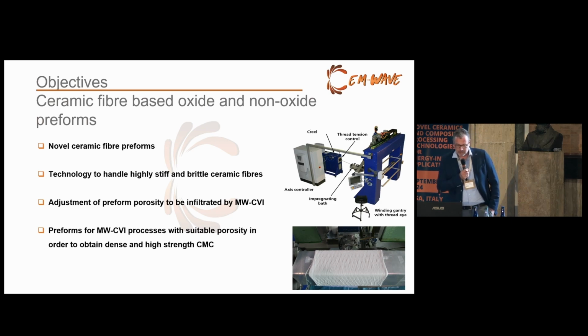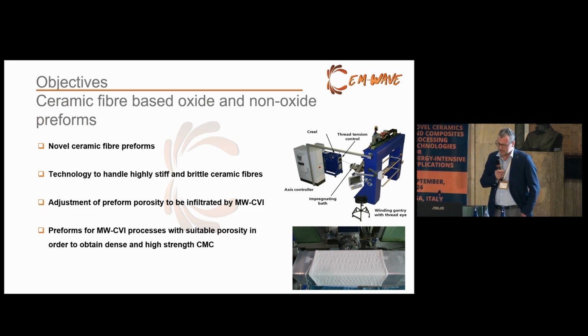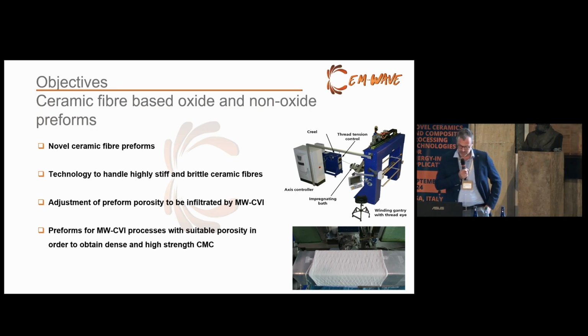So we can handle highly stiff and brittle ceramics because we use cores which have a high diameter, coarser diameter, so your bending angle is quite small so that no fiber breaks. And of course, you can here see a rectangular core, which we also used in the CEM-WAVE project to finally get some plates. We saw there are some problems with this technique.